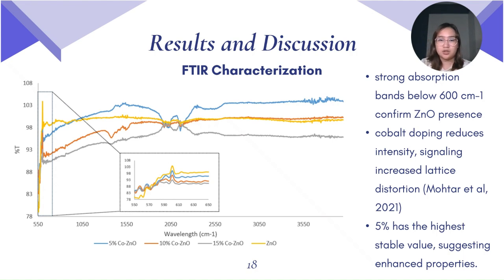The characterization of ZnO and Co-ZnO samples reveals a significant influence of cobalt concentration on the measured property. In the pure zinc oxide sample, there is a strong absorption band below 600 per centimeter, indicating the presence of ZnO and exhibiting a stable baseline. Upon cobalt doping, the peak undergoes a noticeable shift and broadening. For the 5% Co-ZnO sample, the Zn-O stretching vibration shifts slightly, suggesting effective incorporation of cobalt ions into the ZnO lattice, which modifies the local bonding environment.